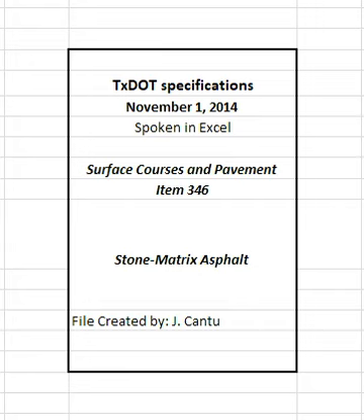4.8 Compaction. Compact the pavement uniformly to contain between 3.7% and 7% in-place air voids. Take immediate corrective action to bring the operation within 3.7% and 7% when the in-place air voids exceed the range of these tolerances. The engineer will allow paving to resume when the proposed corrective action is likely to yield between 3.8% and 8.5% in-place air voids.